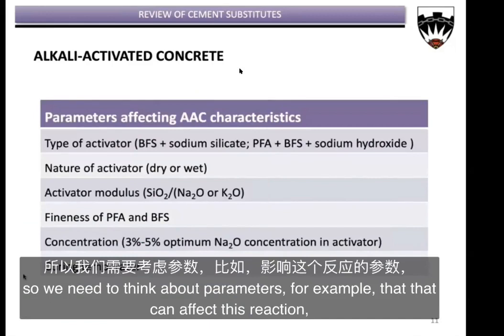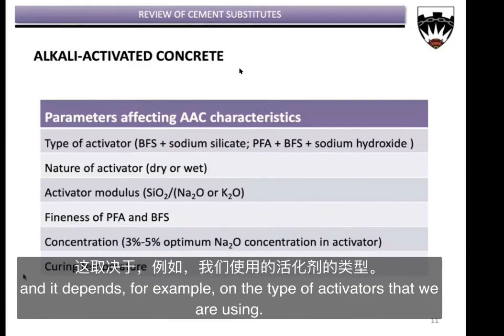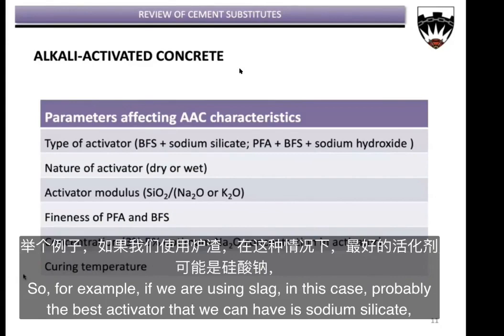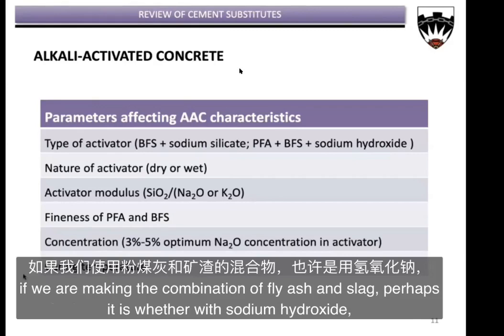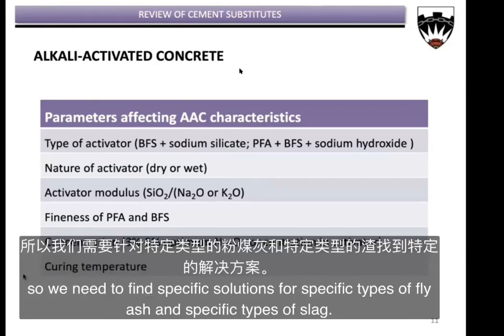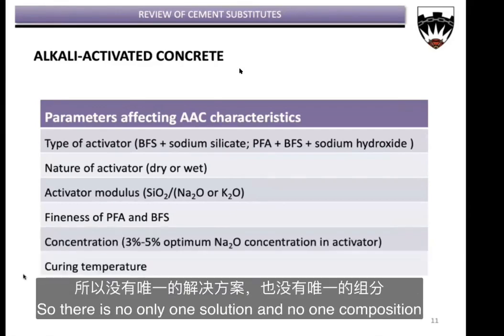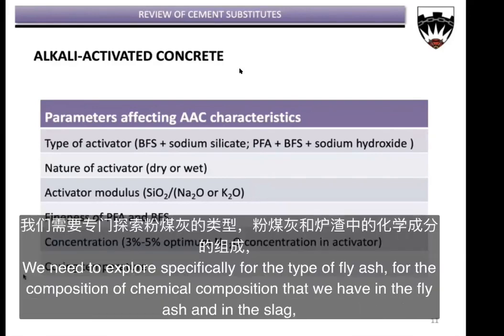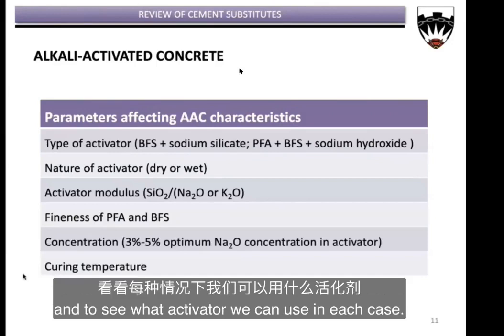So we need to think about parameters, for example, that can affect this reaction. And it depends, for example, on the type of activator that we are using. So for example, if we are using slag, in this case, probably the best activator that we can have is sodium silicate. If we are making the combination of fly ash and slag, perhaps it is better with sodium hydroxide. So we need specific solutions for specific types of fly ash and specific types of slag. So there is no only one solution and no one composition. We need to explore specifically for the type of fly ash, for the chemical composition that we have in the fly ash and in the slag, and to see what activator we can use in each case.